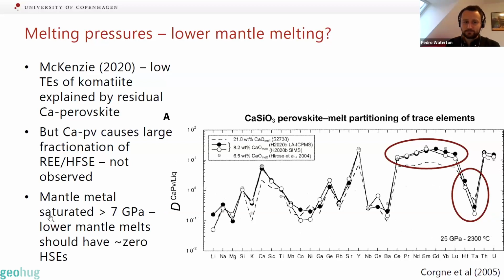The other observation is that at pressures higher than about 7 gigapascals, which is a couple of hundred kilometers depth, the mantle becomes saturated in metal. And so any melts coming from much deeper than this should be basically devoid of highly siderophile elements because they should all stay in the metal phase. And so lower mantle melts should have very, very low highly siderophile element concentrations. This is the opposite of what we see. Komatiites actually have higher highly siderophile element concentrations than almost any other melt on Earth. So I think it's very unlikely that we have this.